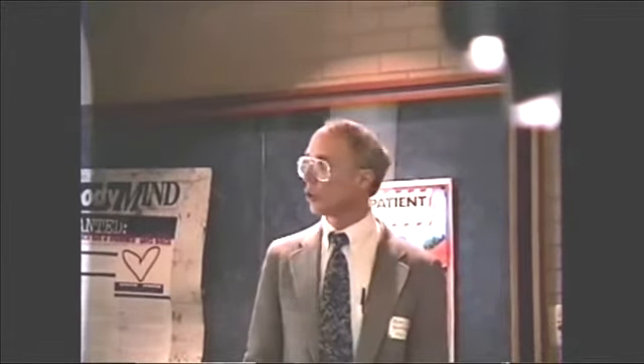Now normally you can regenerate the sulfated zirconia by oxidation. And typically you would expect that that burns coke off the catalyst. That certainly is what I would expect. But now we have a situation where we don't have any coke. So what would heating in oxygen do? Here's an example of a spectrum that was measured after exposure to oxygen at 500 degrees C. There's a couple of things that you can notice here. One is that the intensity in the region corresponding to the sulfur-oxygen double bond is increasing between the used and the regenerated catalyst. The other thing is that the pattern of peak intensities, these two peaks in particular, are transforming from an intensity pattern which is representative of the monoclinic form of zirconia back towards the form for the tetragonal zirconia.